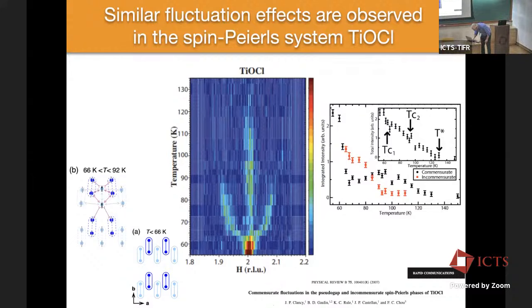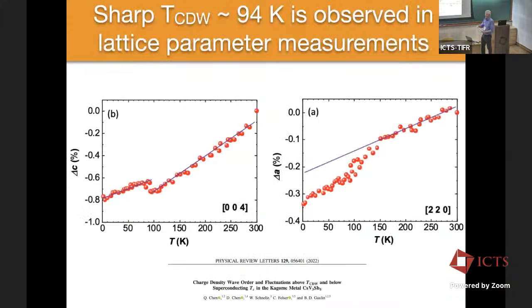So if I go back here, while we're doing these measurements, often when we're changing the temperature, we remeasure the lattice parameter and recalibrate the measurement for the fact that the lattice is shifting a little bit. So as a matter of course, we're always remeasuring the lattice parameter, and this is the lattice parameter as a function of temperature. Usually this is not very interesting, but here you can see that there's a measurable jump as you get to 94 Kelvin. So that shows something at 94 Kelvin.